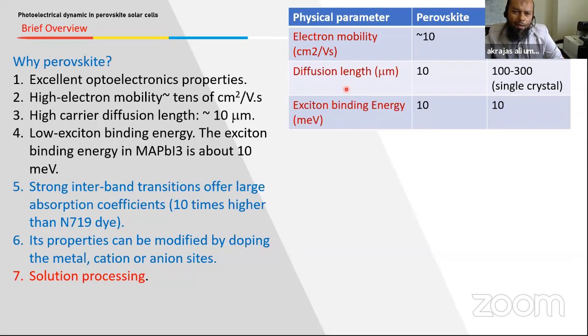Perovskite also offers a high diffusion length, around 10. This is in comparison with single crystal silicon. And actually, depending on the grain size of the perovskite, we can further expand the diffusion length of the carrier inside the material. For example, if we can prepare a single crystalline layer of perovskite, we may get a much bigger diffusion length.